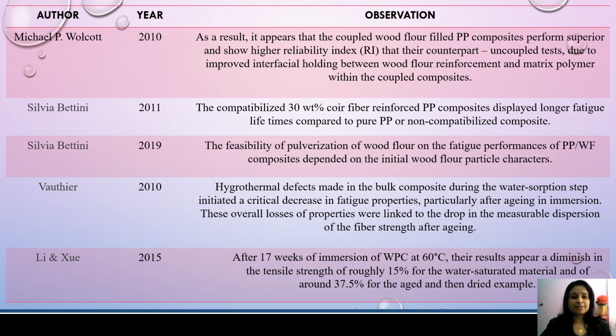Lastly, an experiment carried out by Li and Xue in 2015 showed that after 17 weeks of immersion of WPC at 60 degrees Celsius, their results appear a diminish in the tensile strength of roughly 15% for the water-saturated material and of around 37.5% for the aged and dried example.